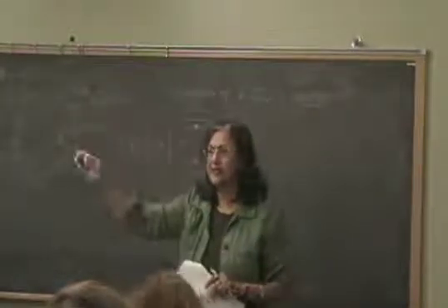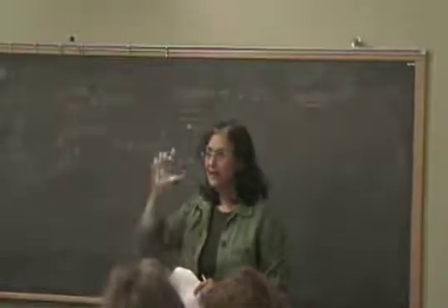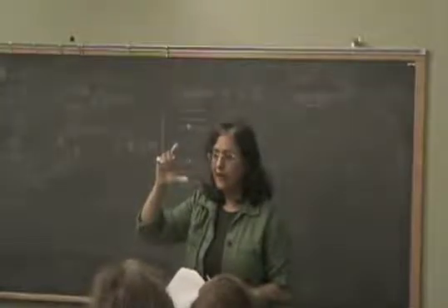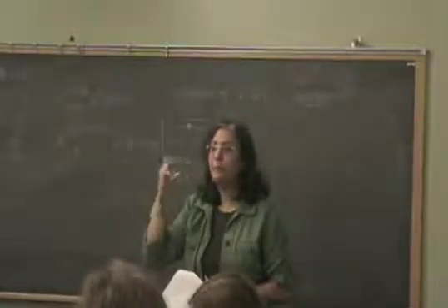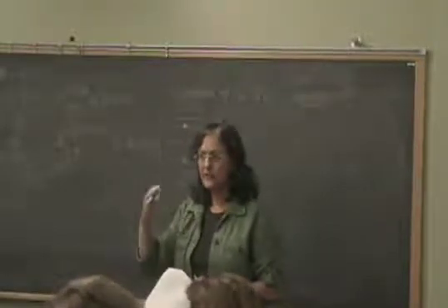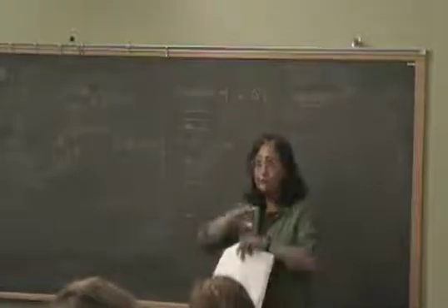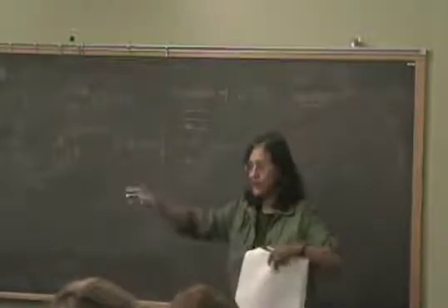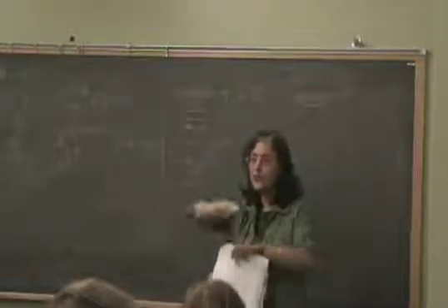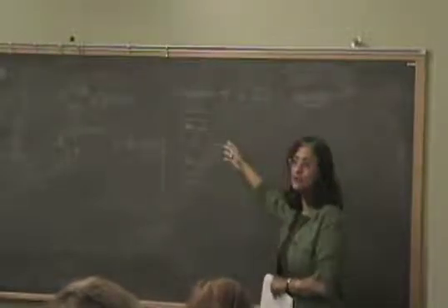You might say, oh, I just put an electron there, it should be running around in plane wave states. But there is a small attraction between the hole and the electron, and that generates a bound pair, like your hydrogenic atom. Now what I want to stress is this happens even in ordinary semiconductors. But the wave functions involved are plane wave states. So you construct this exciton, a bound state, out of plane wave states. So the binding energy is much smaller than in the dot.